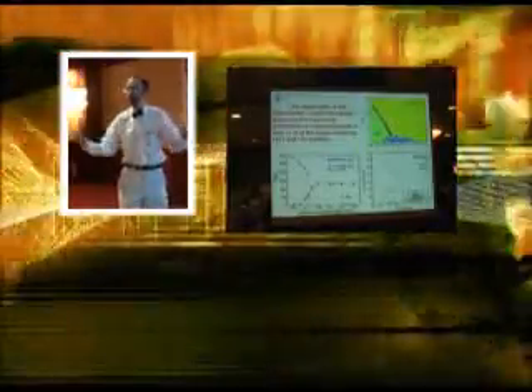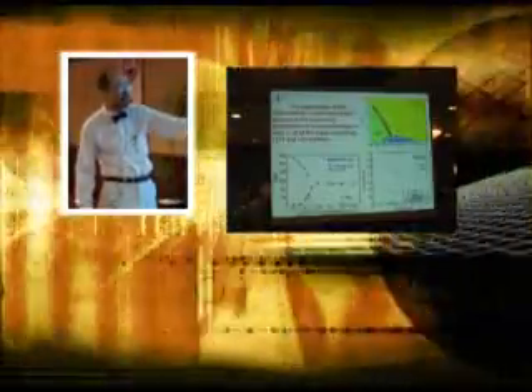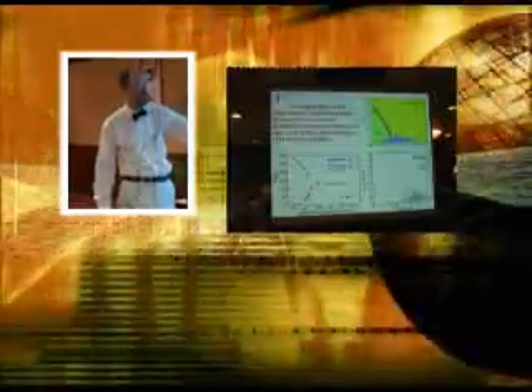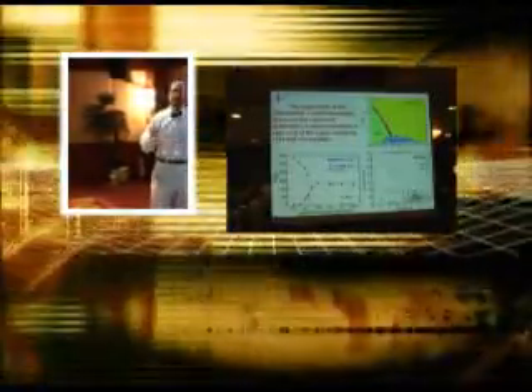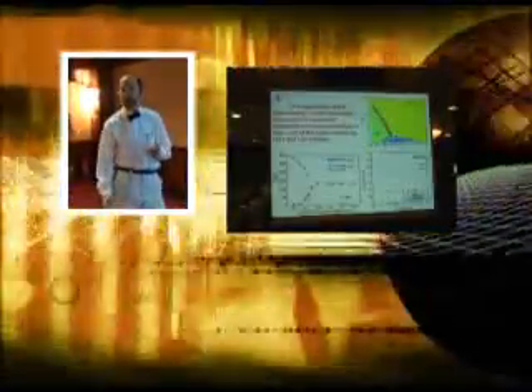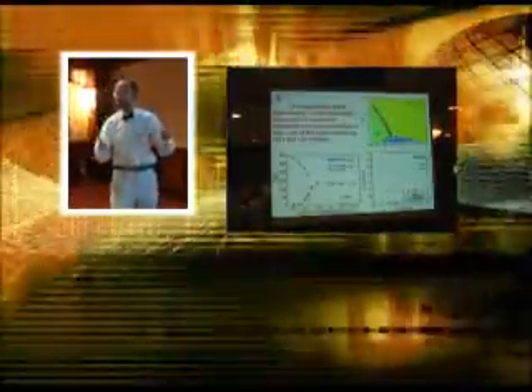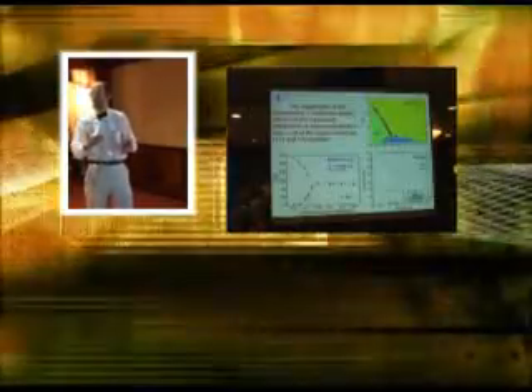And it's not only associated with doping. If you apply hydrostatic pressure, for example, to BaFe2As2 and suppress these upper transitions, you can induce superconductivity as well. So one of the questions is, how are these different perturbations affecting this material and what's governing this superconductivity? I believe it has to do with essentially preserving enough magnetic fluctuations to allow the superconductivity to use that to create the Cooper pairs.